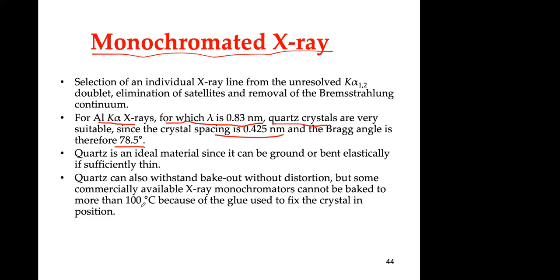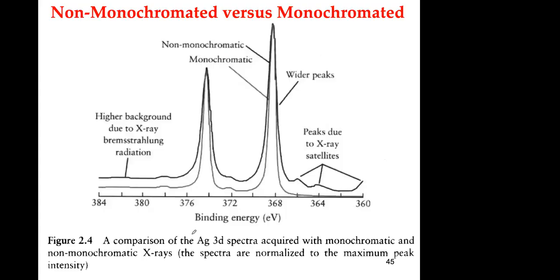This area is very important, and I have not talked about it, but now and then you need to do a bakeout of your system just to purify the interior of your chamber. This is telling you that you cannot heat this whole system more than 100 degrees C because you will destroy the crystal. So you have to be very careful when baking out your system.